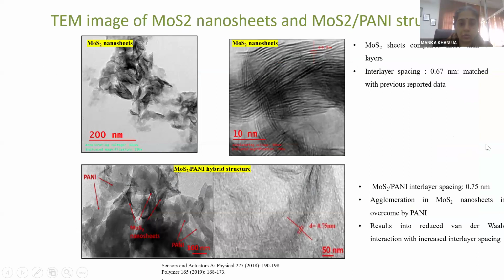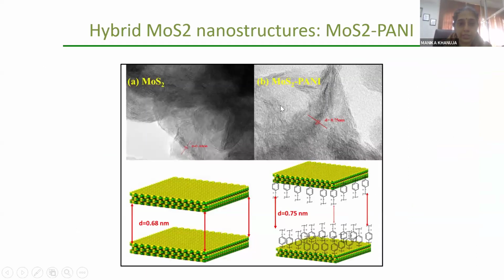I don't want to go further since we are running short of time. Say these 2D nanostructures, we have MoS2 with an interlayer spacing of 0.68, but say we have added something to make it 0.75. Now this interplanar spacing has increased. This is a recently published paper by me, in 2019 or 2020, with more than 120 citations. Here again, this increase in the interlayer spacing we have confirmed through high resolution transmission electron micrograph.